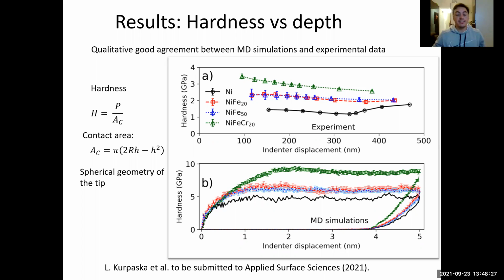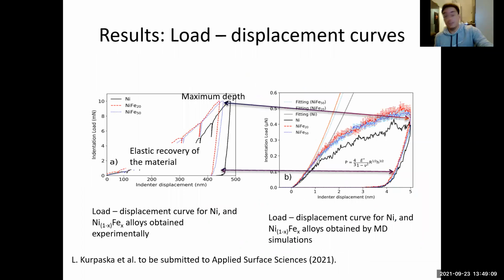Well, we perform many tests. You have the radius of the indenter tip, which is 5 nanometers, and we also test the size of the numerical cell, and we also have the pressure. That's the reason we define different sections for the sample and also the vacuum, and then this periodicity. We notice that the dislocations need to be inside or only around the tip in the so-called plastic deformation region. So you're right. When we have these side effects, you can see here that the load displacement curves don't fit the Hertz fitting, and they also do something random because of the extra pressure that you have. Once we have this Hertz fitting, we are sure that the MD simulation is well performed. Okay, that's a very nice diagnostic.